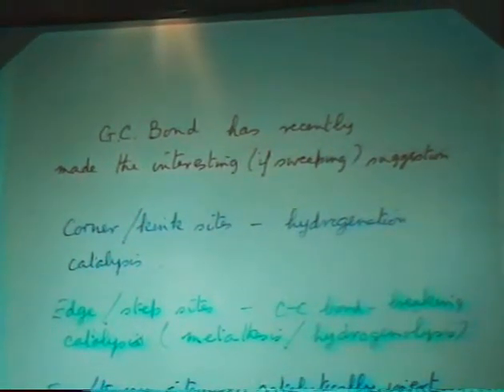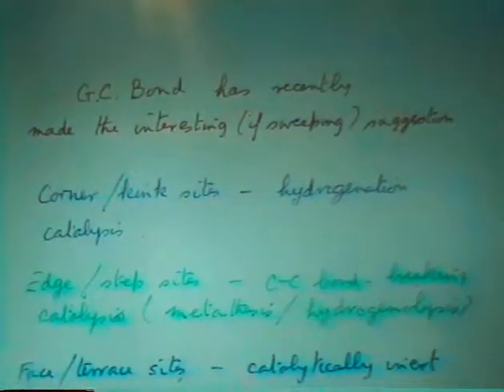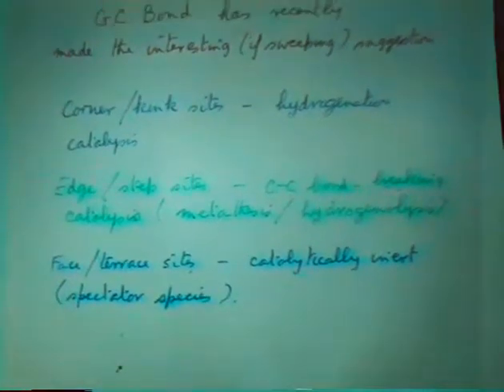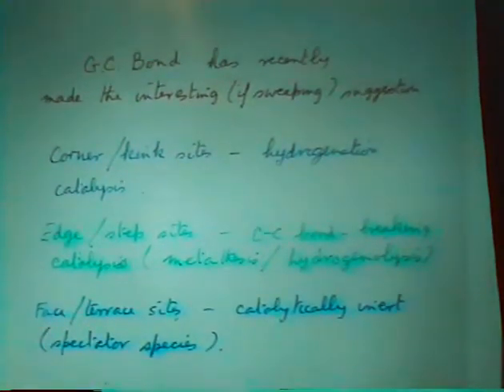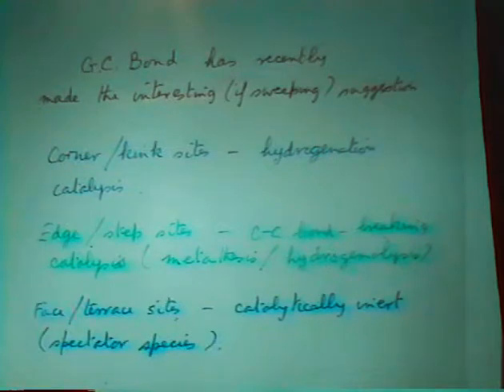I'll just end up with what he would say was a rash generalization that Professor Bond suggested not very long ago: that if you look at metal surfaces, perhaps it's the corner sites which have pi complexes that really matter in terms of the hydrogenation reaction, and all the evidence that we and other people have shown is that the pi complex always goes much the most rapidly when you add hydrogen. On the edge of a crystallite or on step sites, perhaps these are the CC bond breaking sites, which lead ultimately to hydrogenolysis or metathesis. And from the catalytic point of view, the terrace sites, the flat planes, are really rather inert.